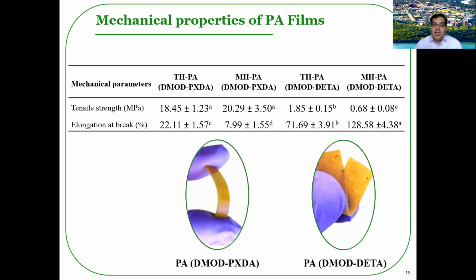However, the percent elongation at break of the traditional polycondensed semi-aromatic polyamides was almost 3 times more than the one produced under the microwave radiation. Regarding the linear polyamides DMOD-DETA, traditional polycondensed linear polyamides had the higher tensile strength, while the microwave polycondensed linear polyamide had a higher percent elongation at break in comparison with their counterparts. These differences could be due to the differences in the molecular weight, polydispersity, and the crystalline structure of the polyamides produced under different heating methods.